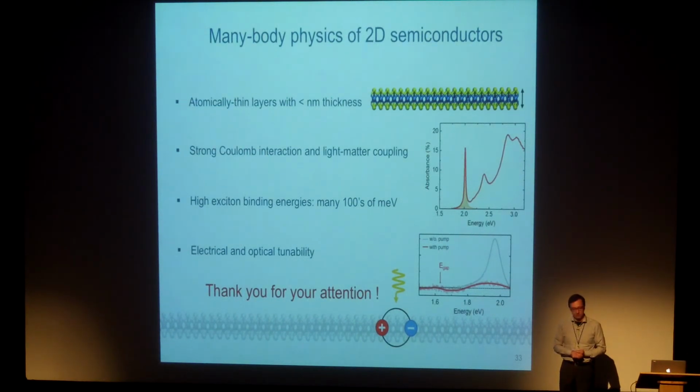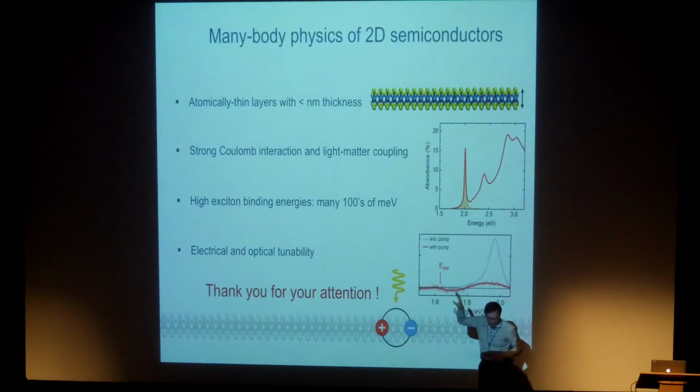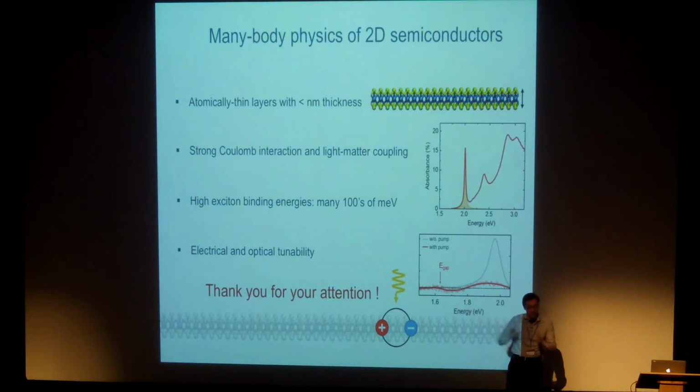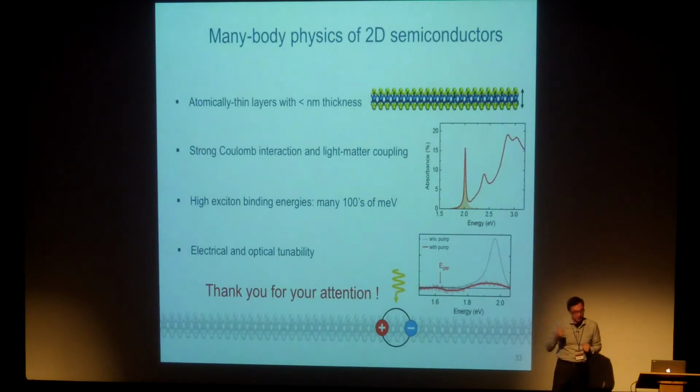That's why it has energy that's lower than the conduction band. It will be promoted. So if we look very closely, and thanks Andrew for clarifying it a bit, if we look closely at the spectra, at this difference between exciton and trion feature, it will resemble the core binding energy, what Andrew said, of this extra electron only at zero doping conditions.